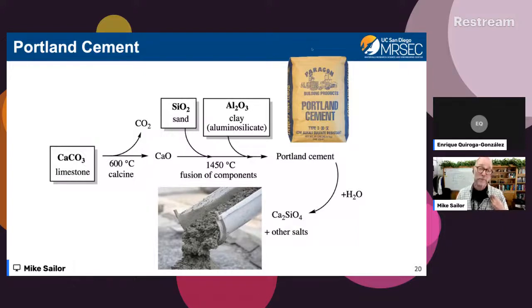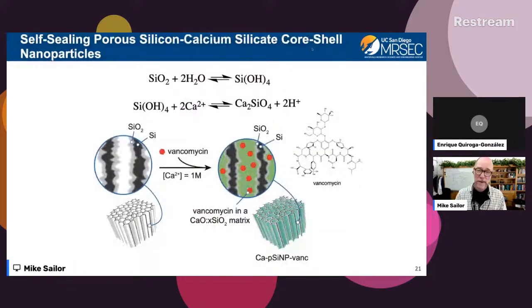Now, our silicon nanostructures aren't made of sand, but they do have silicon dioxide in them. And so that top reaction shown on the slide here is just the simple hydrolysis chemistry of silicon oxide. When you put sand in water, it'll form, to a very small amount, this silicon tetrahydroxide, or silicic acid as it's called. That's the top equation. And the second equation shows the precipitation reaction, basically the same reaction that occurs in concrete or in cement. And that is, silicon tetrahydroxide reacts with calcium ion to make calcium silicate. And so in the presence of our nanostructures, remember I told you that our silicon nanostructures are dissolving continuously when they're in water. They make silicon oxide, they make the silicon hydroxide.